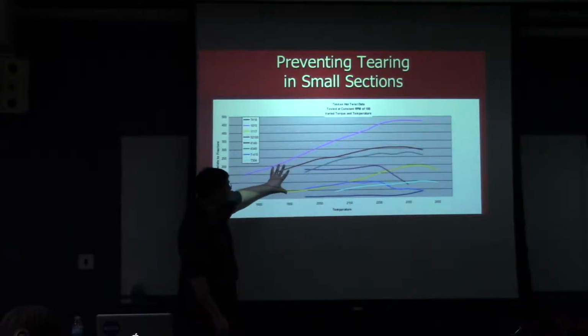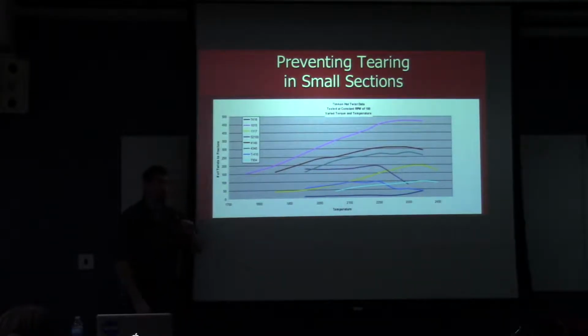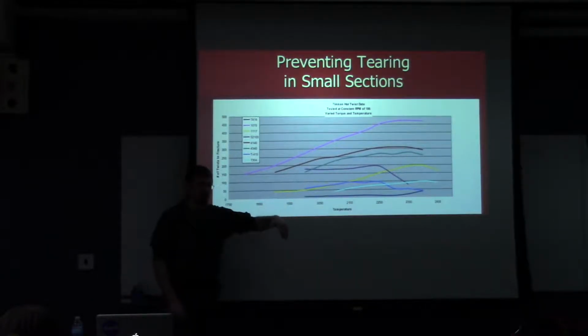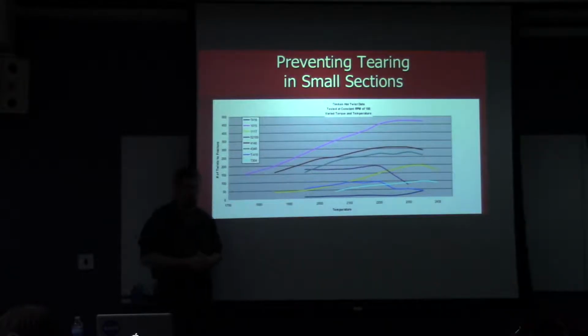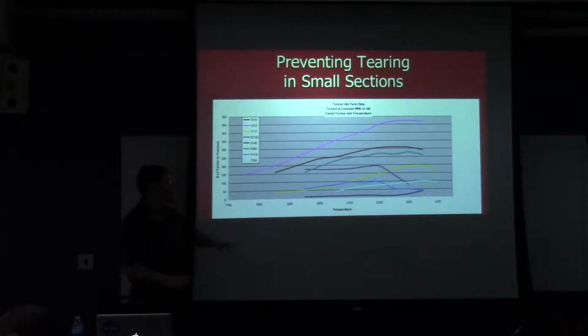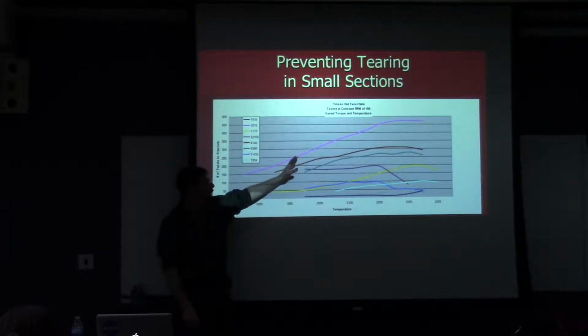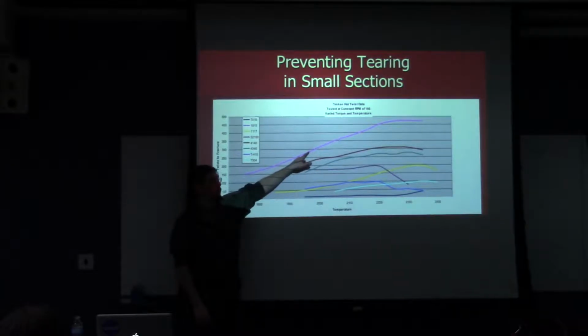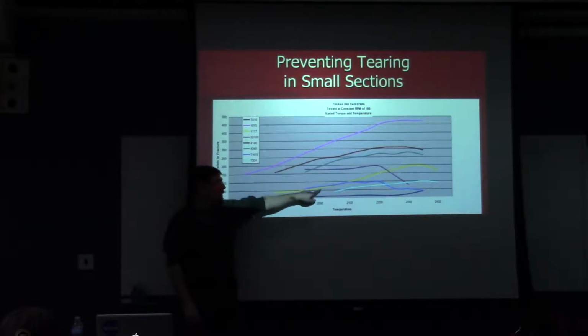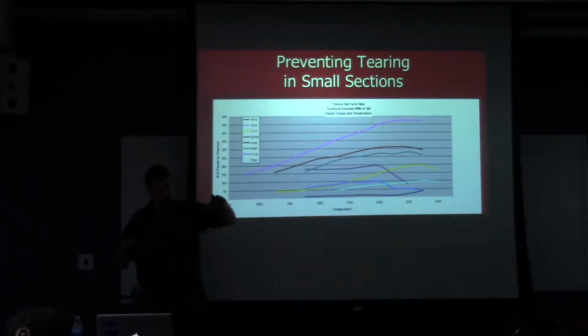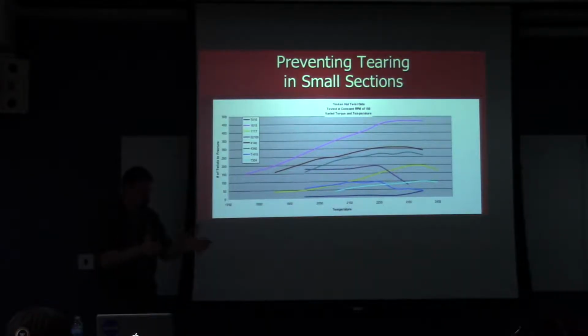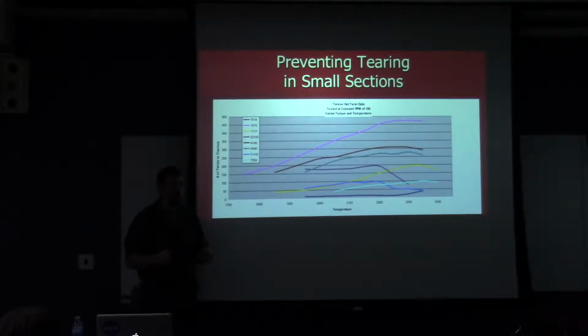the 1015 and the 1117, so these two are nearly identical materials, with the exception that this one here, the 1117, has sulfur added back to it, which is great if you're a machinist. It allows you to use faster speeds and feeds. Machinists like that. But from a forging perspective, what this shows me is that this material here will be able to withstand a lot more centerline shear and centerline tensile stress than this material here. So as a forging operator, I need to know what I'm working with and understand how to adjust my technique based on the material type that I have.